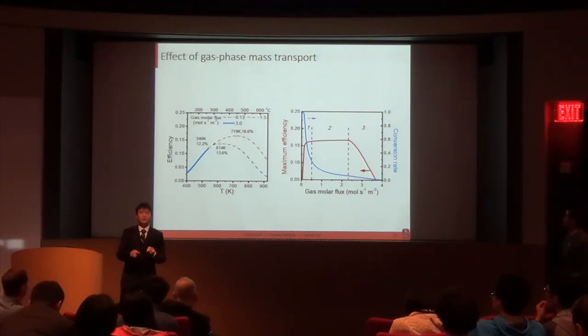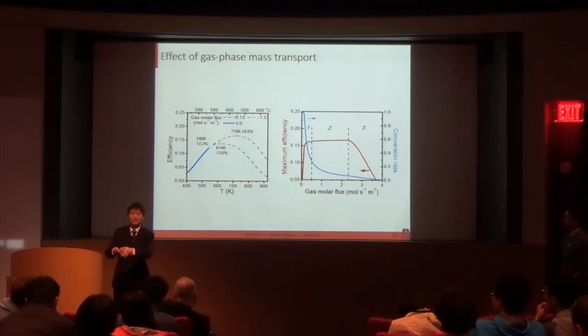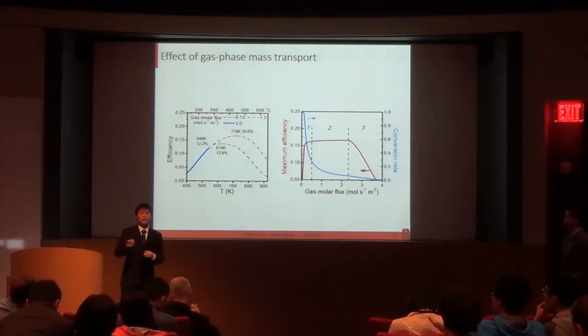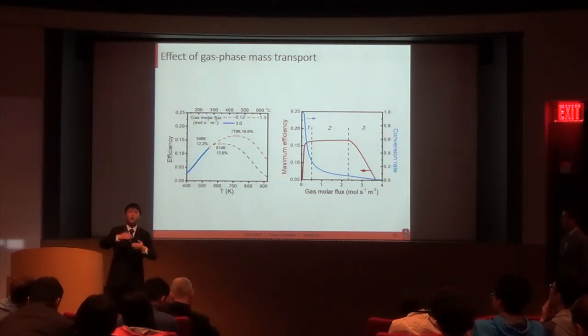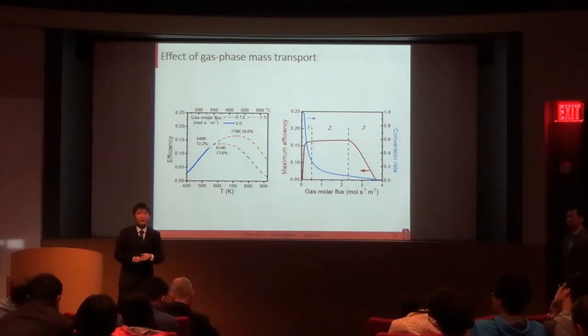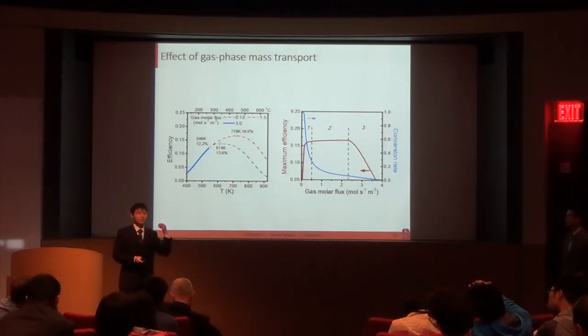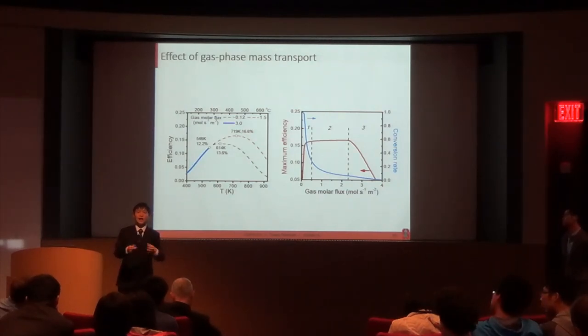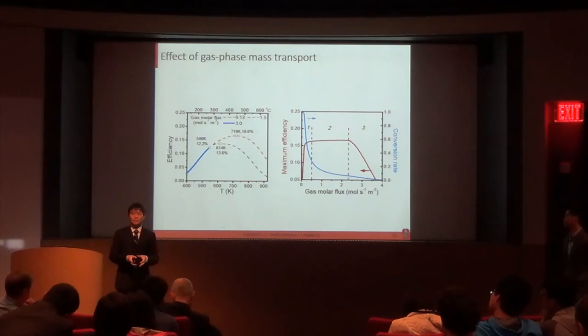One typical way is you can put porous platinum on top of the electrolyte. So you share the same electrolyte, but you have a side electrode with platinum and use that as a reference electrode. I've tried that, but it doesn't seem to work very well, maybe due to the reversibility of this electrode. But that's a very good question that we need to think about. So right now we are just doing the two electrode mode, not the three electrode mode. And the good thing is, since we are doing the photoanode, the cathode, which is the hydrogen evolution reaction, is usually much faster, or more reversible, than the anode.